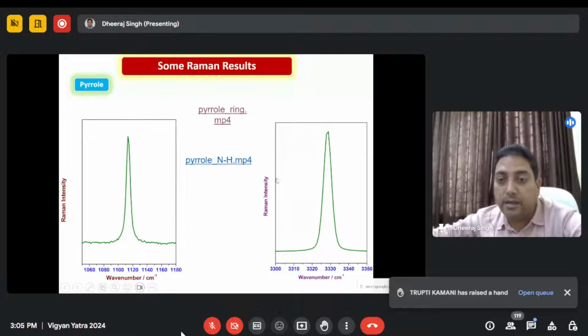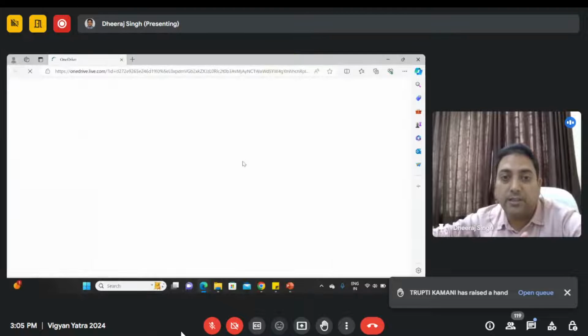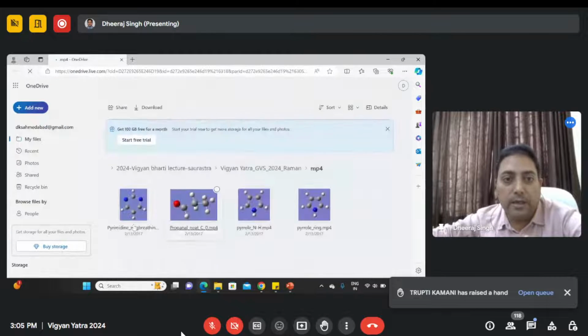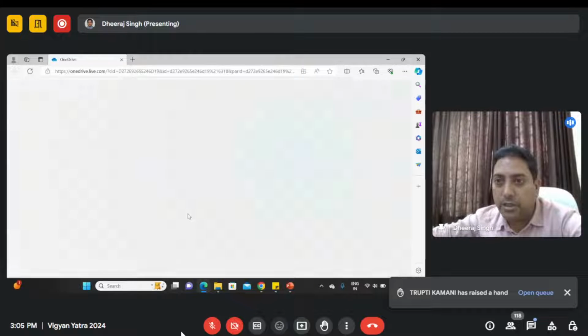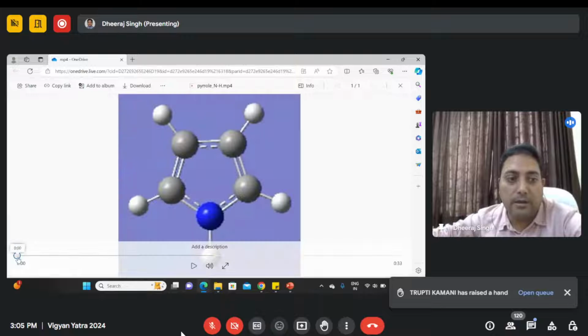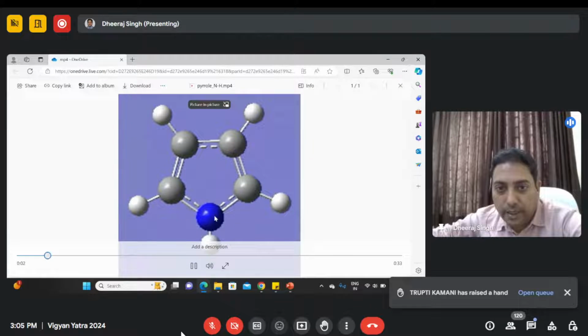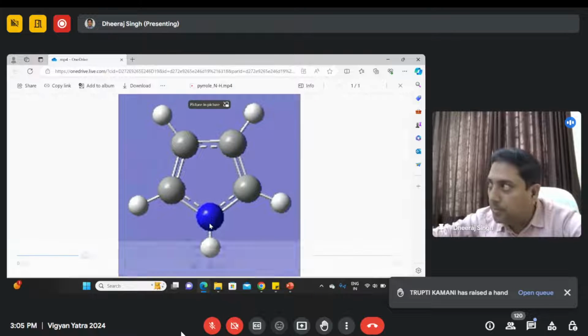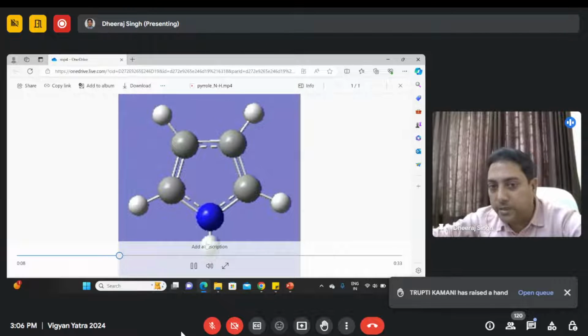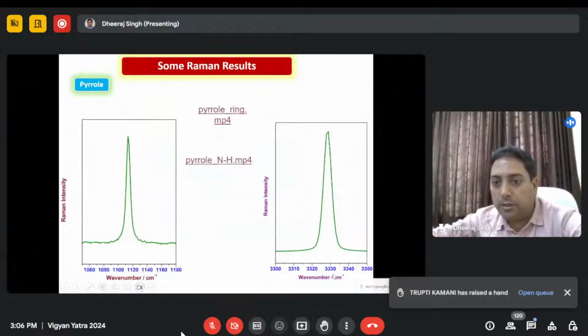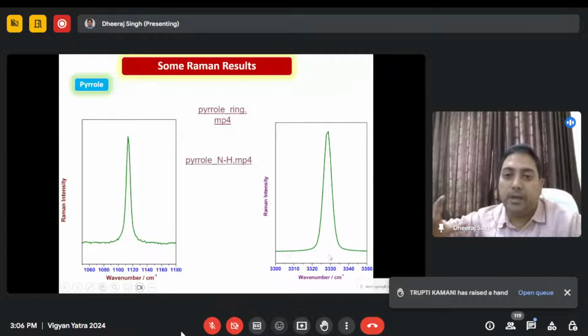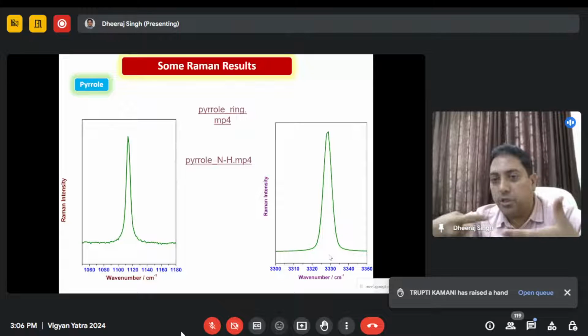Now in pyrrole, we can see there is another peak, the NH stretching mode. NH stretching mode means that there is an NH bond stretching at a certain frequency. Now this NH frequency is larger than 1600 centimeter inverse. So we can see that the pyrrole molecule has certain vibrations in the NH stretching region. Only this NH bond is vibrating, and due to these vibrations we are getting a Raman peak at around 3300 centimeter inverse. Now, if any molecule interacts with this pyrrole, your NH stretching vibration will be affected. So after observing changes in peak position, line width, and intensity variation, we can analyze our Raman result.